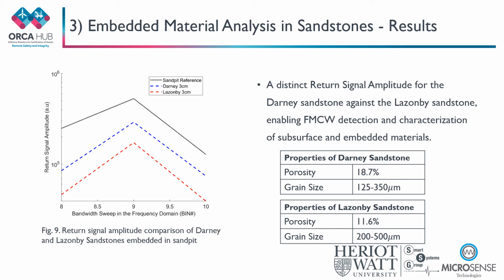The Lazonby, on the other hand, has a significantly lower observed porosity at 11.6%, which is considerably lower than the Darney sandstone. This is due to the sample being dominated by highly cemented, grain-supported, fine to medium-sized spheroidal, sub-rounded grains and well-sorted quartz clasts ranging between 200 to 500 micrometers. The Lazonby sandstone contains mainly quartz and orthoclase feldspar with some clays and very much the same proportions of the Darney sandstone. However, the iron content is more dispersed throughout Lazonby when compared to Darney sandstone, although the magnitude is similar. The figure highlights a distinct return signal amplitude for Darney sandstone against the Lazonby sandstone, which enables for FMCW detection and characterization of subsurface materials.